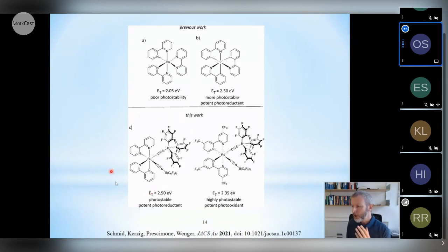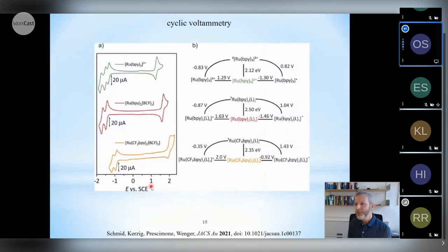So we applied a concept here that in principle is well known. Vincent Ko, for example, at City University of Hong Kong, had worked on cyanoborated rhenium complexes, also iridium complexes, a while ago. And we have now applied this recently to ruthenium photophysics and photochemistry in order to achieve high triplet energies. And the way this works is perhaps best illustrated here by these cyclic voltammograms.